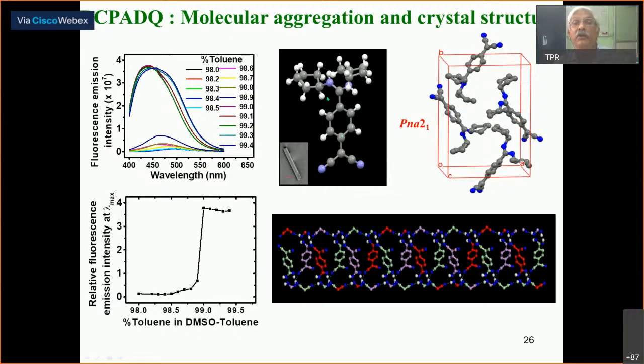you can get the molecular structure, crystal structure and so on. And this is very important. The most important point here is the space group that it belongs to. I'll just note that it is a non-centrosymmetric crystal space group, which will be relevant in trying to understand this phenomenon. At least that is what we believe at the moment. And they have nice hydrogen-bonded structures and so on.